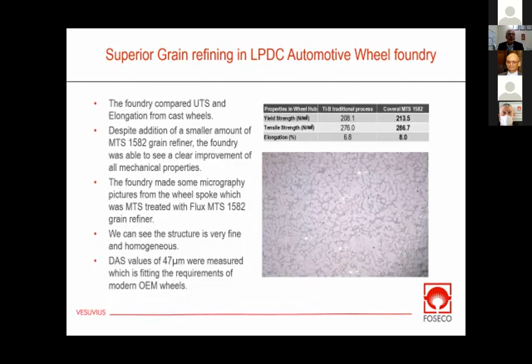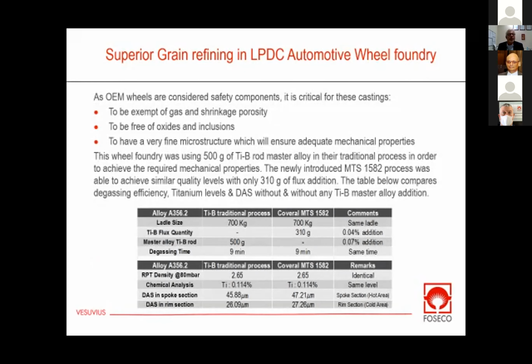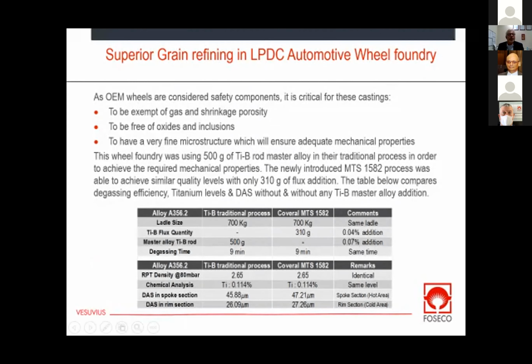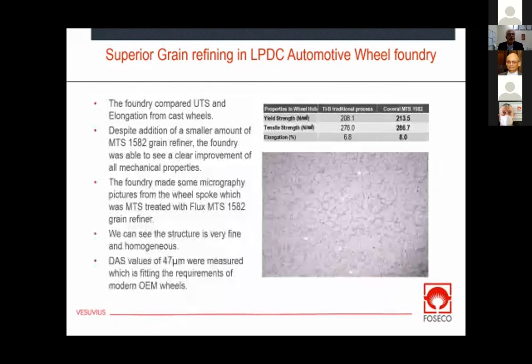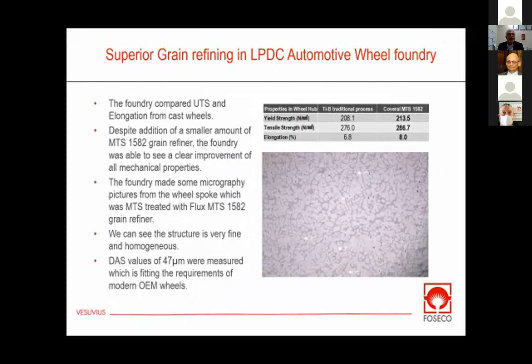The first reason is the improvement of mechanical properties, which we were able to demonstrate. The second is the reduction in addition rate, which you see here: 0.07% for the Ti-B versus 0.04% for ours. So for the foundry, this represents a saving—a lower cost when it comes to grain refining. This is a very important aspect for wheel foundries.